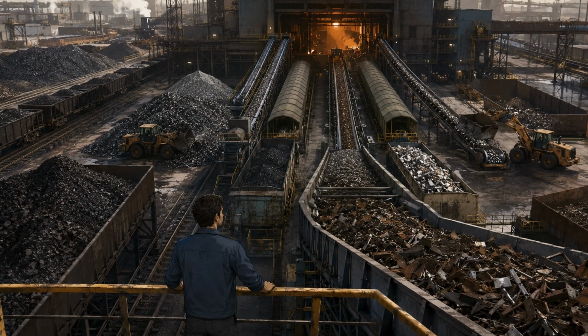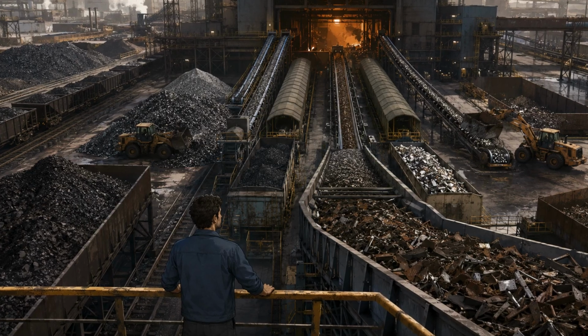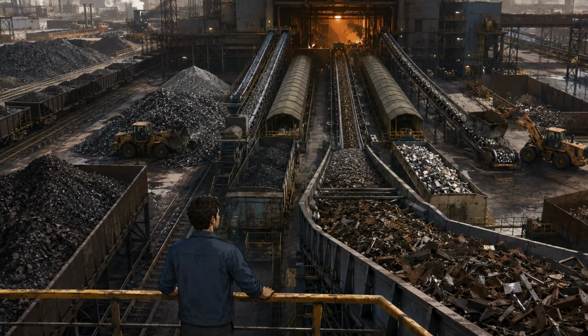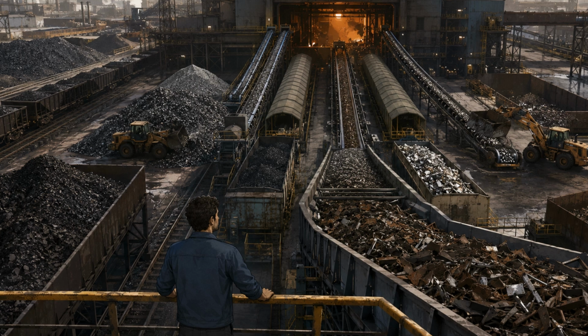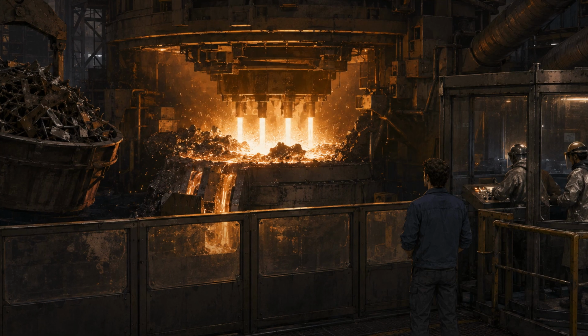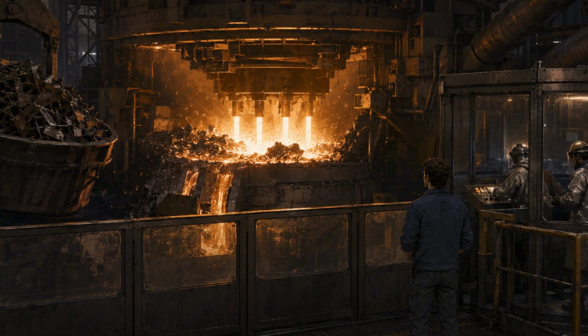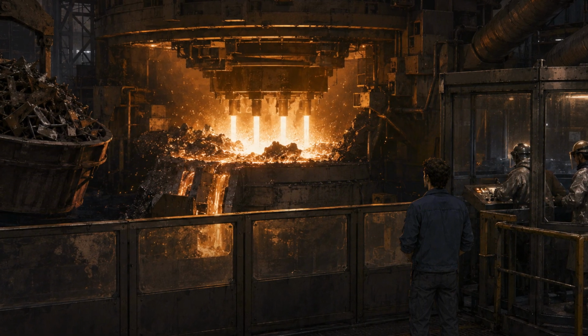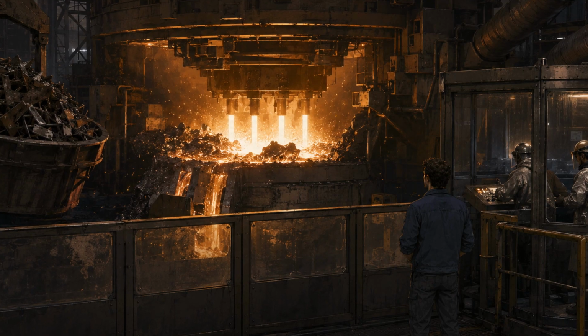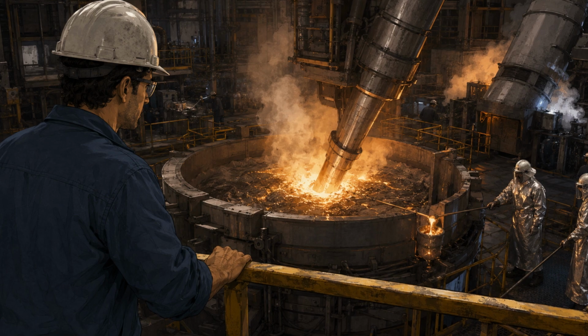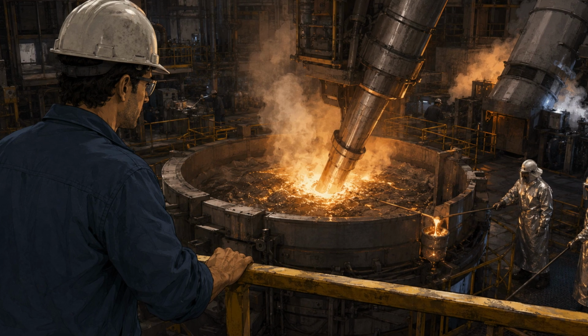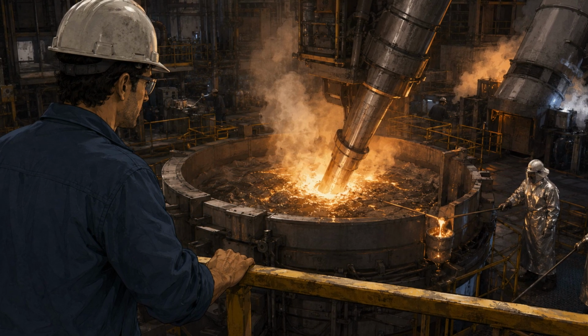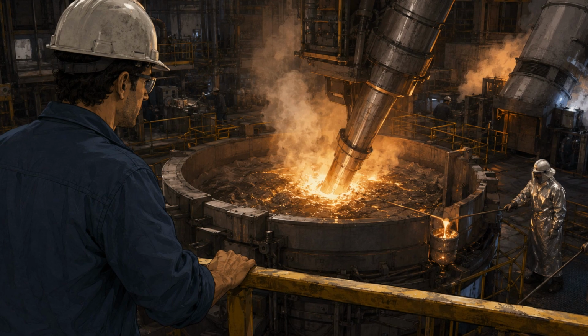Turning that conditional chemistry into millions of reliable objects begins far from the finished shine. Chromite becomes ferrochromium. Nickel, molybdenum, iron, and recovered scrap enter different grades through global supply chains. At a steel plant, an electric arc can melt scrap and other metallic feed. The difficult task is removing unwanted carbon while keeping valuable chromium in the metal. Modern decarburization vessels control oxygen with inert gas or reduce pressure. Operators adjust temperature, chemistry, and slag until the melt fits a narrow composition range.